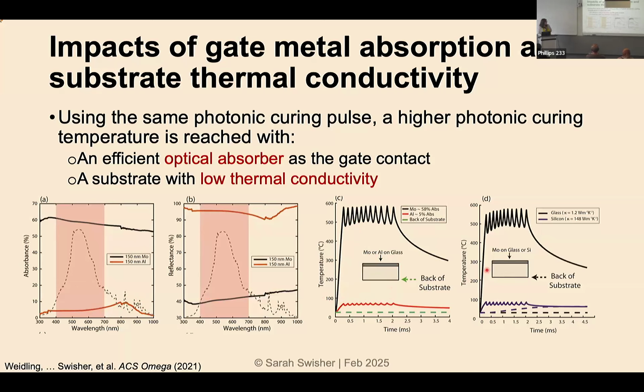The second choice of material has to do with the substrate. So here, I'm showing a molybdenum absorber layer, and we're looking at the substrate as being either silicon or glass. A lot of the early work here was done on a silicon substrate with an aluminum gate. And what we're showing here is that because silicon is so thermally conductive, it sucks the heat away, and you don't actually heat up the top surface of your film. So with the same pulse and the same molybdenum gate, you can reach about 500 degrees if you have it on glass, and you reach, again, only about 100 degrees if you have that molybdenum on silicon. So you have to structure your devices with intention so that you can take advantage of this photonic curing.